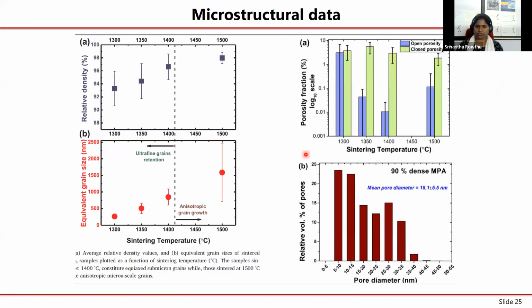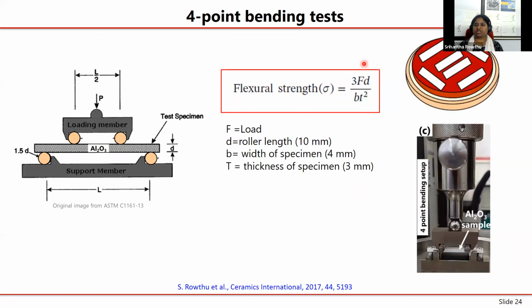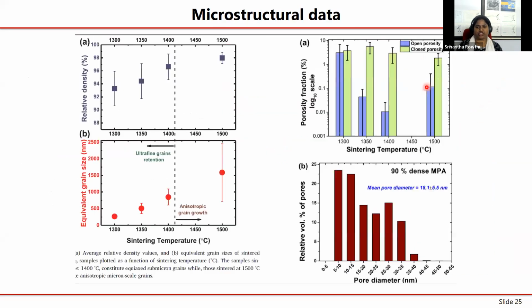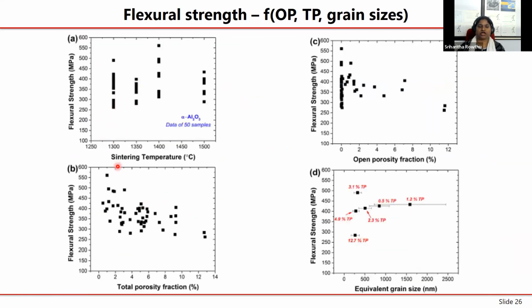So we have done it, and again, these are characterizations, because do remember that once you have different dimensions, and if you place them in the same furnace, then again your microstructural properties can be different. So one has to know all the properties like pore fraction, density, grain sizes, etc. for different sintering temperatures. So that's okay. Then we will look at the flexure strength data. So totally, I have made 50 specimens in total. So look at this. This particular batch of samples is for 1300 degrees Celsius sintered samples. Another one is 1350, 1400, and then it's 1500.